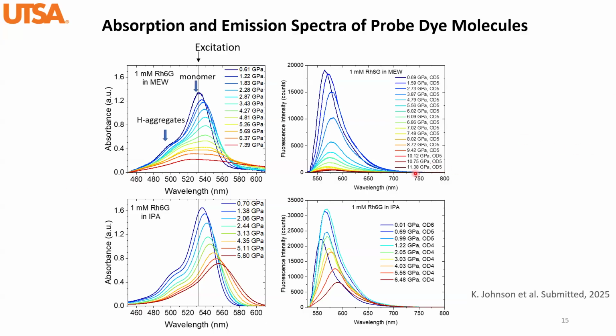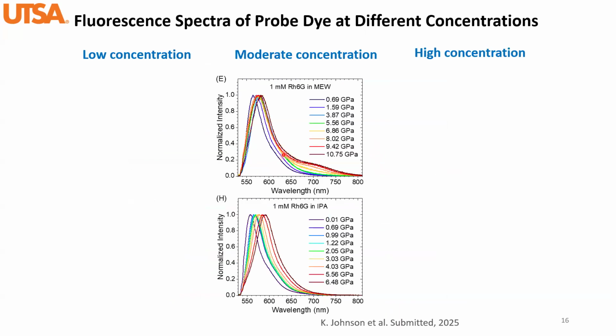So this is not really obvious here, but when we do a peak-normalized fluorescence intensity, we actually see some tiny little feature around 700 nanometers for the rhodamine 6G in methanol, ethanol, and water. We have been trying to wonder why that is, and it looks like it's probably the emission from the aggregates that were not perfectly aligned. So when the H aggregates are not perfectly aligned, they can still emit light. Combined with the absorption spectrum, we believe that this is emissive H aggregates.